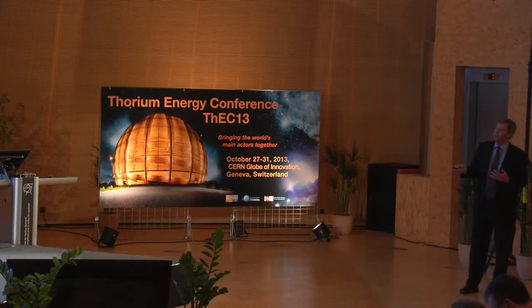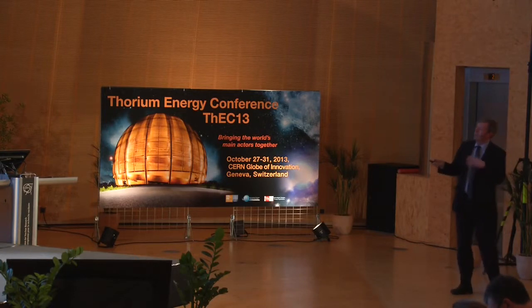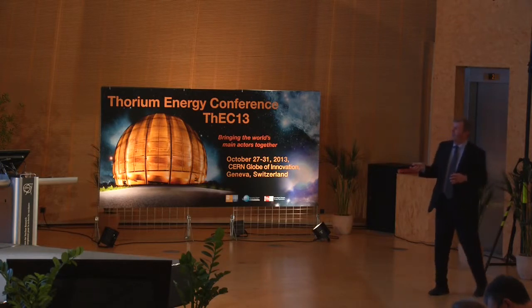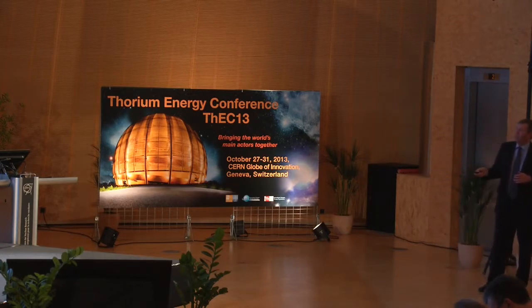So you're trying to go from some initial concentration of element M, initial concentration of element N, to a final composition of element M, where you haven't deposited any of the element N. So the separability would be, if you could achieve this, and this was a very low mole fraction in the solvent, you would have separated M from N. Now it turns out that the separability in this system depends upon standard electrochemical potentials, electrodeposition potentials of the metals, say with respect to their pure molten salts, but also on these so-called activity coefficients.